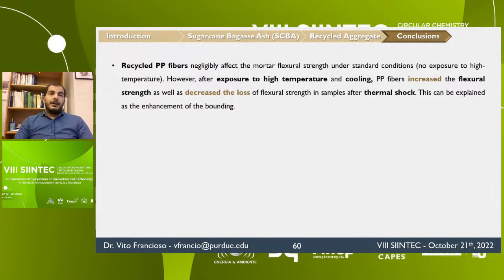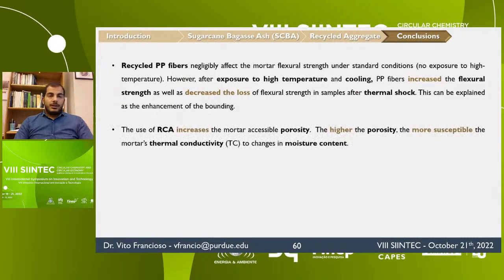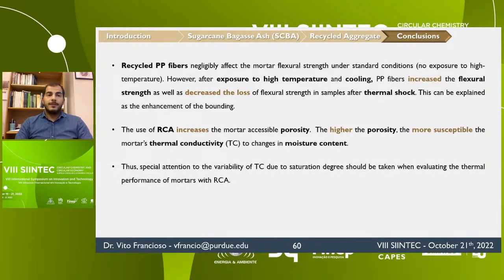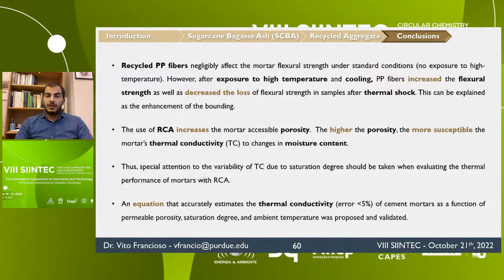Finally, the use of recycled concrete aggregate increases the mortar accessible porosity, and the higher the porosity, the more susceptible the mortar's thermal conductivity will be to changes in moisture content. Thus, special attention to the variability of the thermal conductivity due to the saturation degree should be taken when evaluating the thermal performance of mortars with recycled concrete aggregate.